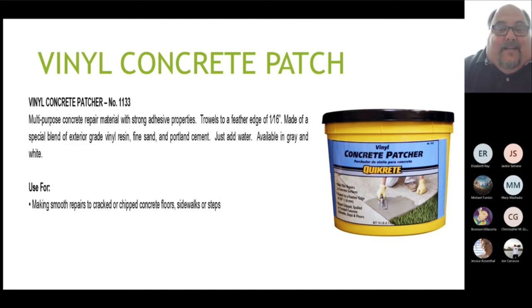You want to stick within about a 10 square foot area when using this product. You don't want to surface a whole slab with it. This is usually for if you've got a tree root growing up and a little separation, where you need to make a little ramp out of it, or you have a pop out or a spall or a chip in the concrete. This works perfectly because it mixes up just like peanut butter, a plastic consistency.